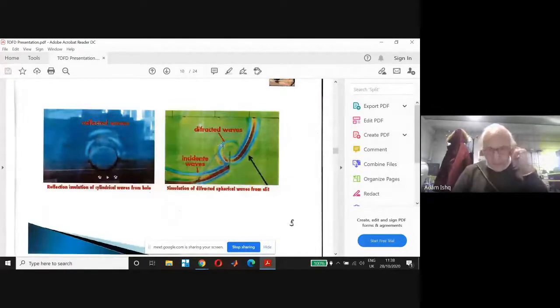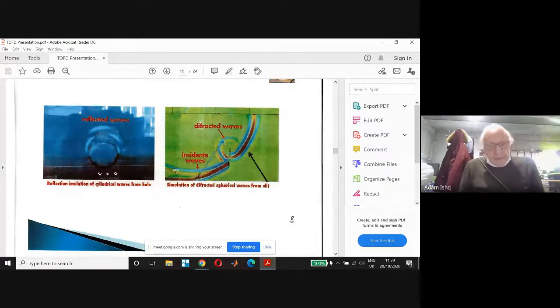Okay, on the left you see a simulation of a cylindrical wave, completely different, so it's a front line, they go back, there is no spherical wave. This is typical for volumetric defects like slag inclusion, porosity, and the right one is typical for cracks, lack of fusion, and lack of penetration. Next one.